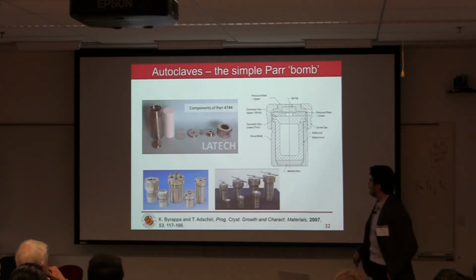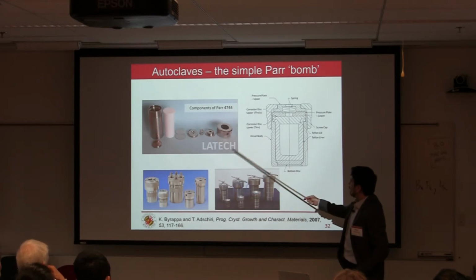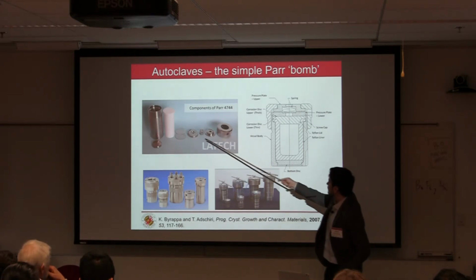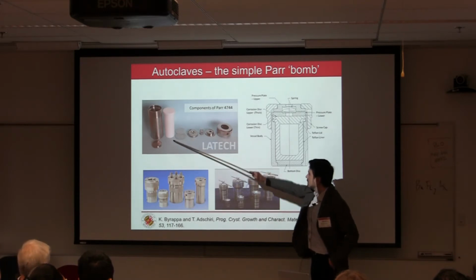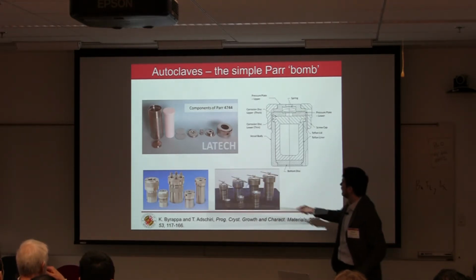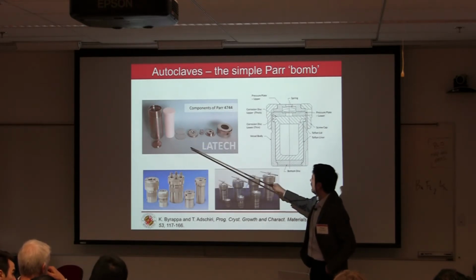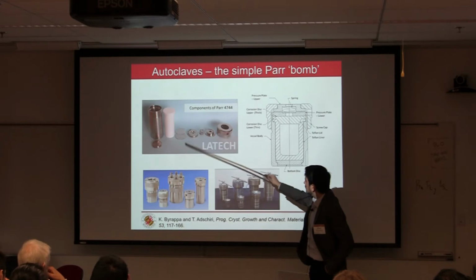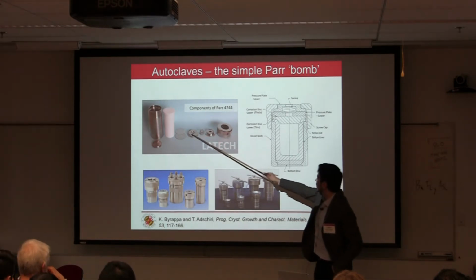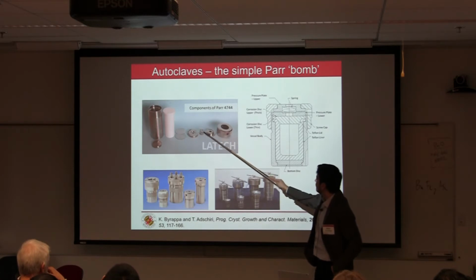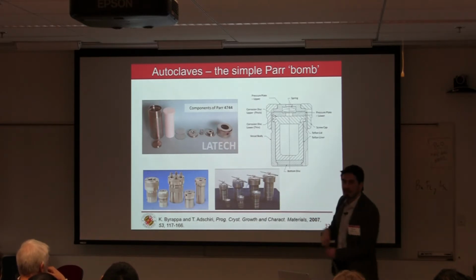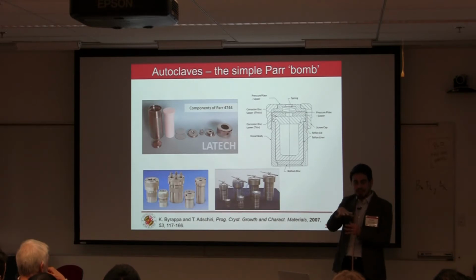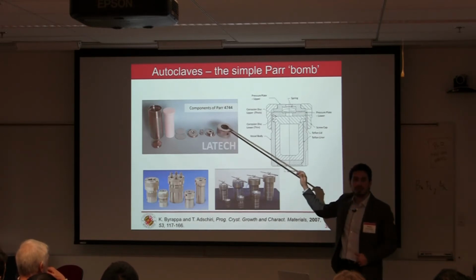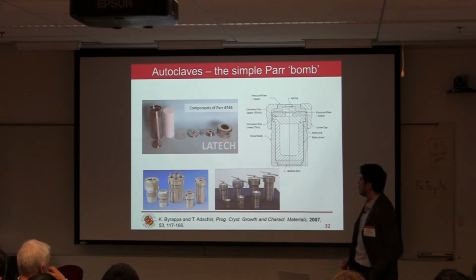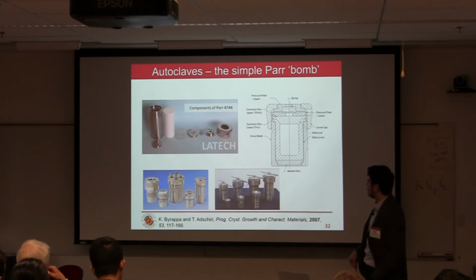And so these are typical components that you get from a Parr bomb. This is the autoclave, and this is a 45 milliliter Teflon cup. You have the cup itself where you load all your reagents, and you have these little plates in case you get a leak in the autoclave. They're there as a safety mechanism, and then you get a spring-loaded top that, when it starts to actually boil, it seals the Teflon cup, and so all the pressure is autogenous, coming from the bomb itself. So it's self-sealing if you put all the components on correctly, so that you don't lose your solvent with temperature.